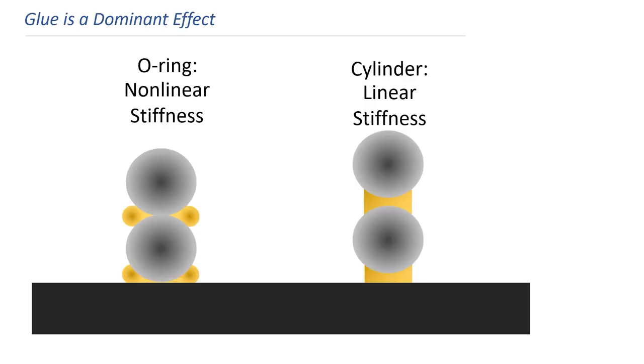Another interesting thing we've observed from our experimental testing of our microgranular crystals is that the glue that joins the spheres together can play a dominant role in determining their mechanical behavior. Crystals with O-ring-shaped glue joints, which hold their spheres stacked together but still allow them to make sphere-on-sphere Hertzian contact, achieve the desired nonlinear stiffness response more closely than crystals that consist of the X-shaped or solid cylinder joints as shown on the right. The reason is that these joints separate the spheres sufficiently enough so that they don't directly touch and thereby achieve a more linear mechanical response with the Young's modulus that more closely mimics the modulus of the glue than the modulus of the silica spheres themselves.